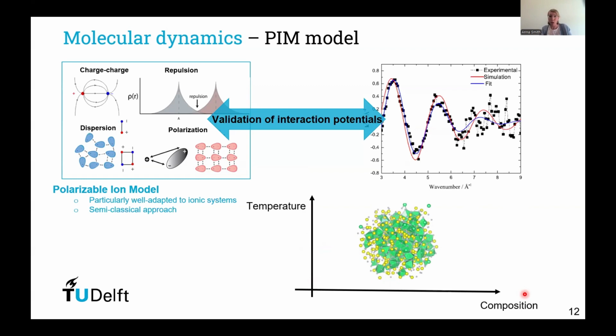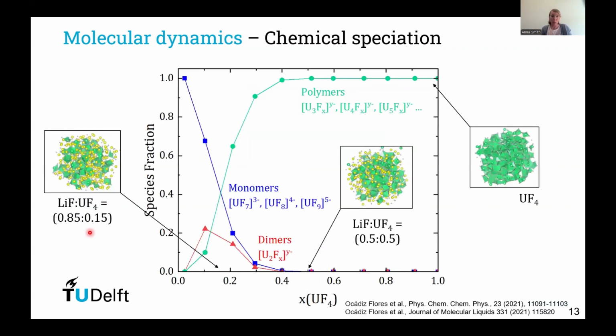We have followed this approach, for example, for a lithium fluoride, uranium fluoride mixture. And after the experimental campaign and after the molecular dynamic simulations, we could see that the chemical speciation of the salt varies a lot with composition. At high lithium fluoride content, we have mostly monomeric species of uranium fluoride that are 7-fold, 8-fold, and 9-fold coordinated. And when we increase the uranium fluoride content, we start to form dimers, trimers, tetramers, and eventually polymeric chains. So we have a fully connected network here.